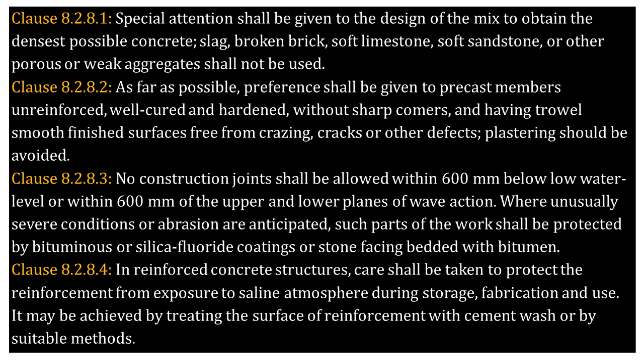Clause 8.2.8.3. No construction joints shall be allowed within 600 mm below low water level or within 600 mm of the upper and lower planes of wave action. Where unusually severe conditions or abrasion are anticipated, such parts of the work shall be protected by bituminous or silica fluoride coatings or stone facing bedded with bitumen.